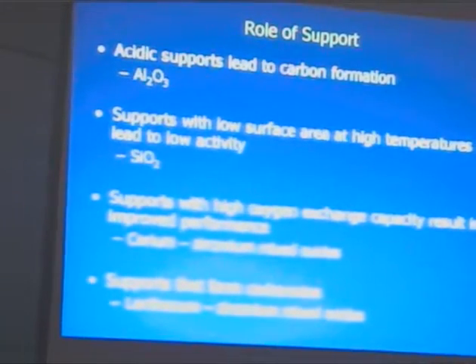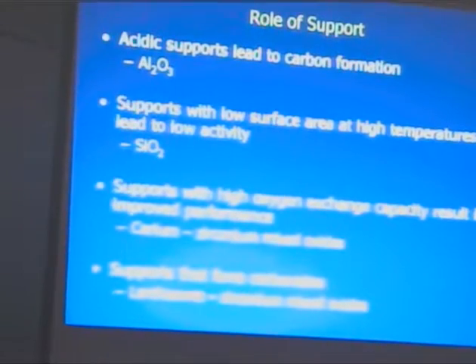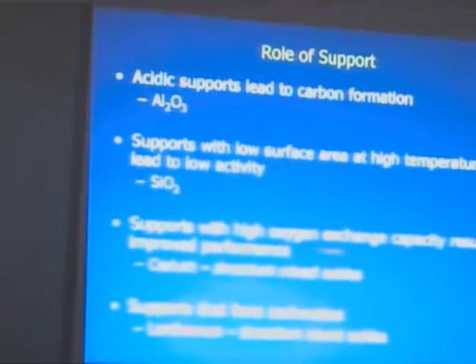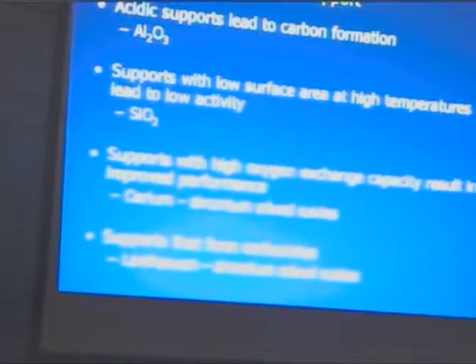When you start going up to 800, 850, 900 degrees, supports with high oxygen exchange capacity, and we used ceria and zirconia promoted catalyst supports with platinum on those materials, and showed that you could see increased stability and increased activity with the promotion of ceria with zirconia. That promotion came from the fact that the oxygen exchange aided in the removal of carbon or the cleaning of the metal, and I'll talk about that further.